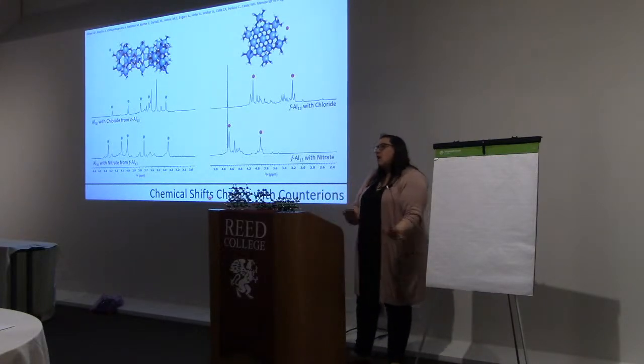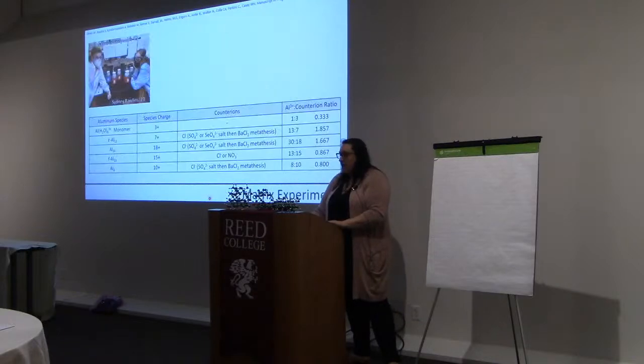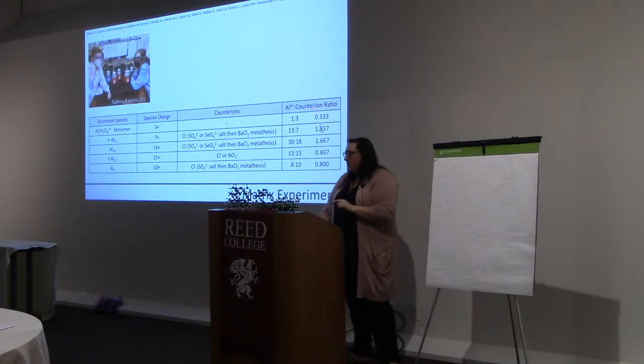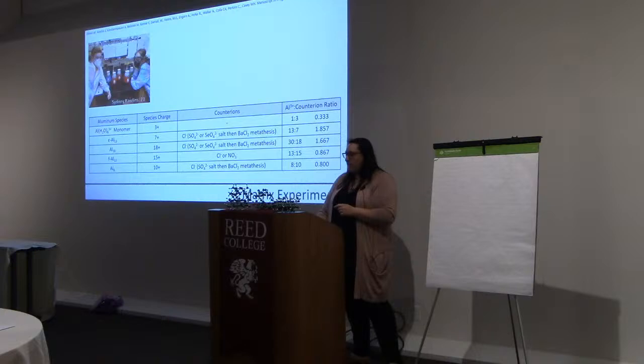This next set of experiments, we went from looking at dissolving clusters to dissolving monomer and seeing what clusters naturally self-assemble in solution, okay? So if we look at the clusters that I told you already, our epsilon, our 30, our flat, and our 8, which we haven't been able to synthesize, and we look at their charges versus the number of aluminum atoms, we can get these ratios. Aluminum to counterion, if we're thinking of a charge of -1 for our counterions, so chloride and nitrate. And we get this variety of ratios. Our monomer is 0.33, our clusters that have the tetrahedral signal are both above 1.5, and then our flat class clusters are 0.8, 0.9, right, as the ratio.